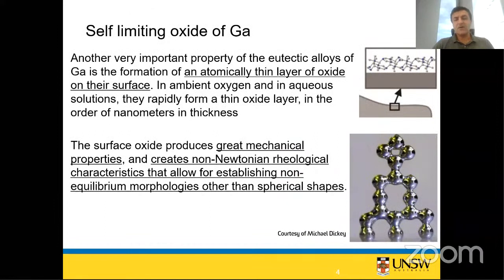Now, gallium has other interesting properties that mercury, for instance, doesn't have. Gallium in ambient oxygen, 21% oxygen, produces a self-limiting oxide on its surface. This oxide becomes only 1 or 2 nanometers thick and it stops, and it protects the bulk of the gallium from further oxidation. It's a two-dimensional material, very similar to graphene. It's very strong across the two dimensions. What does it mean? It means it can hold things together. You can print small droplets of liquid metal on top of each other. As you see, it's a 3D print. You go up and up and up and make 3D objects, but before it collapses, you can make this kind of print.